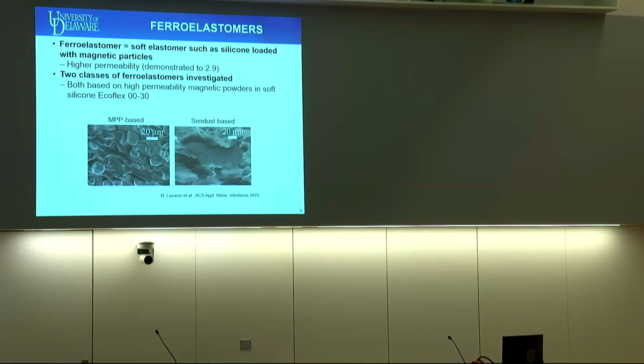And this is a relatively simple material. Just think of taking something like silicone and just stirring in magnetic particulate. We looked at a few different types of particles, but the one on the left is something called permalloy powder, which in this case was about 30 micron spherical particles within the silicone. The one on the right is more of a flake-type geometry, about 100 micron platelets of another high permeability material known as sendust. And both of these were just stirred into the soft silicone Ecoflex 0030.